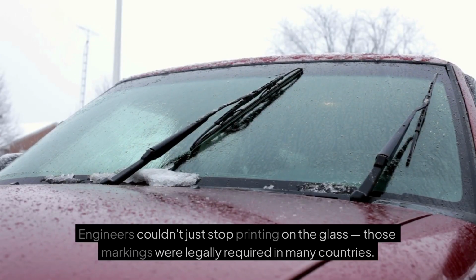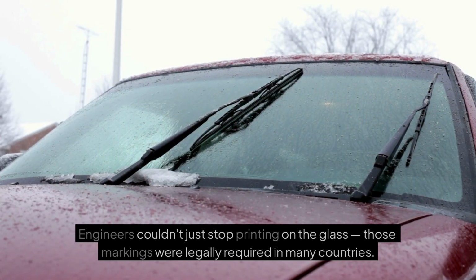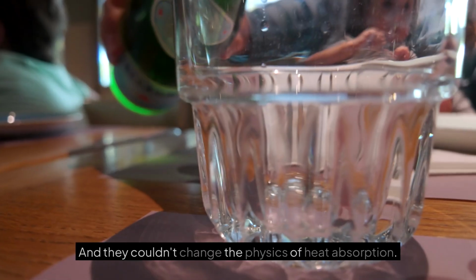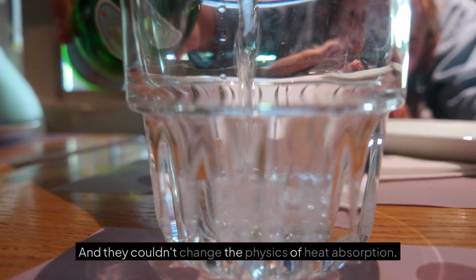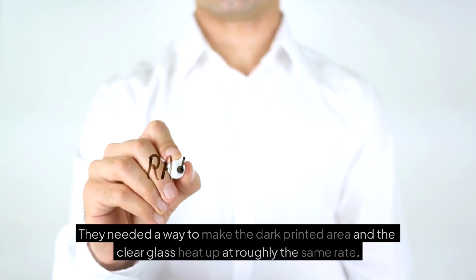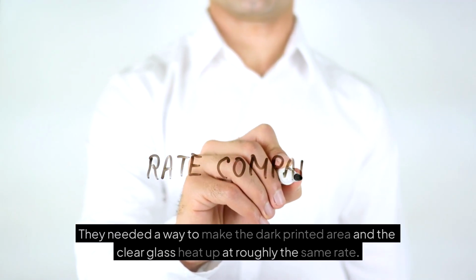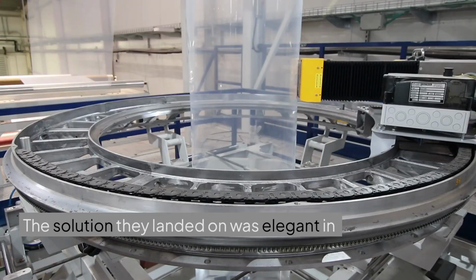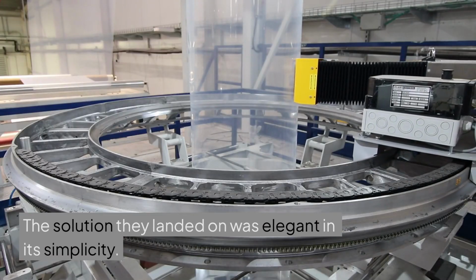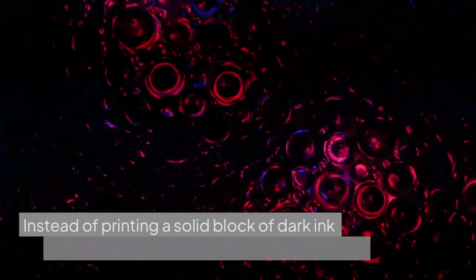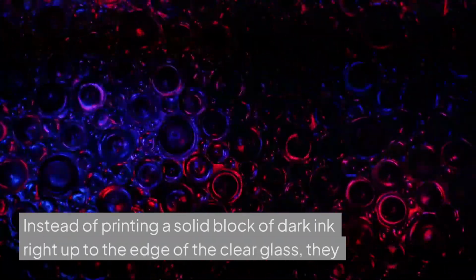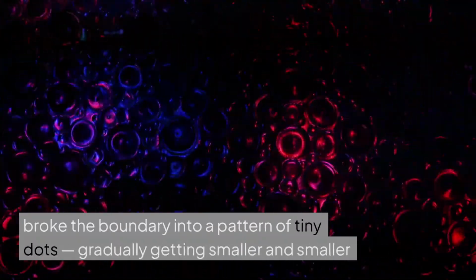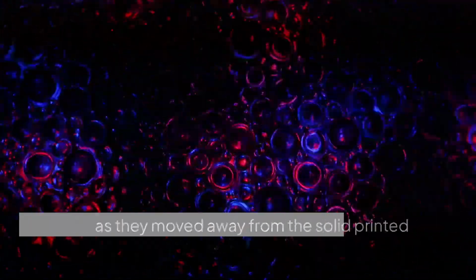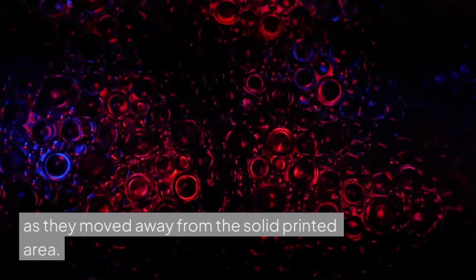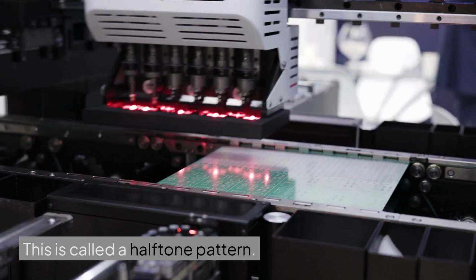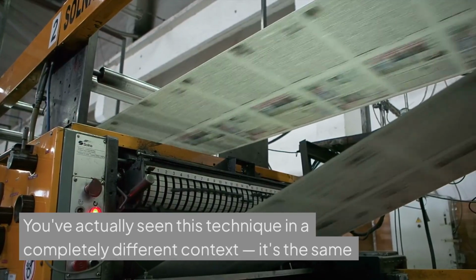Engineers couldn't just stop printing on the glass. Those markings were legally required in many countries. And they couldn't change the physics of heat absorption. They needed a way to make the dark printed area and the clear glass heat up at roughly the same rate. The solution they landed on was elegant in its simplicity. Instead of printing a solid block of dark ink right up to the edge of the clear glass, they broke the boundary into a pattern of tiny dots, gradually getting smaller and smaller as they moved away from the solid printed area. This is called a halftone pattern. You've actually seen this technique in a completely different context.